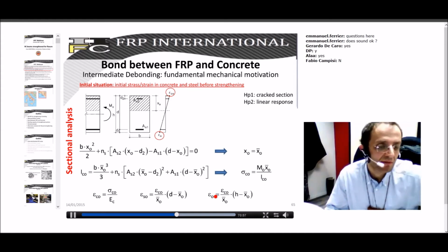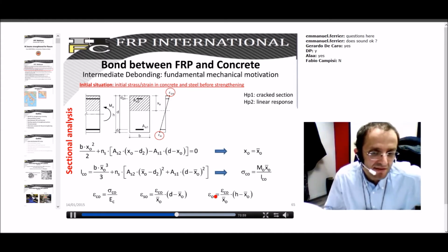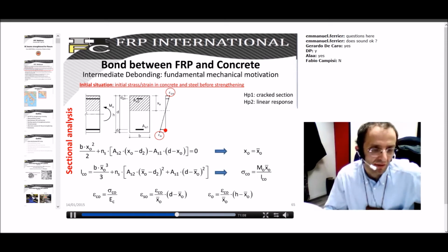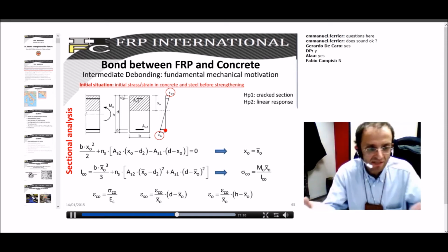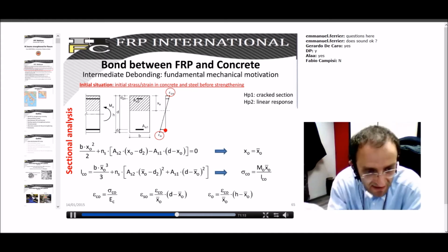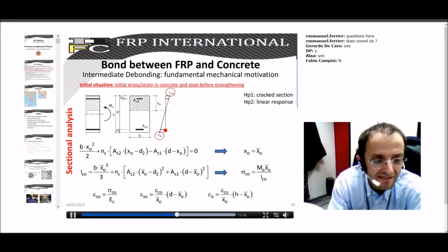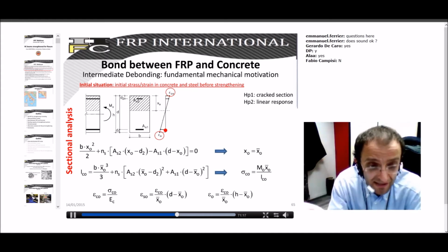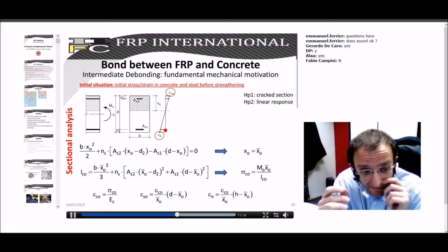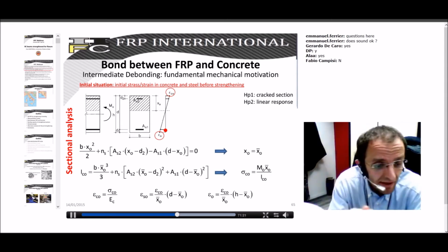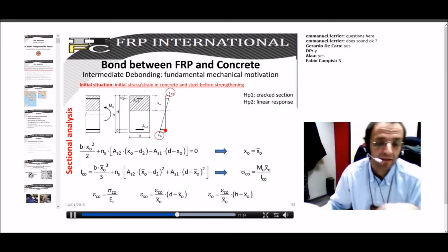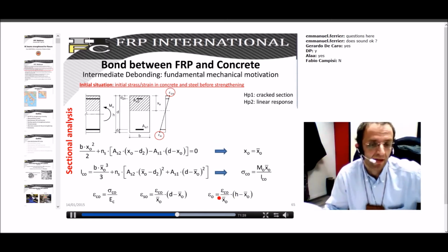Epsilon zero is an important parameter because this is the epsilon which is developed in the bottom chord of the section when you apply your FRP strip. So the FRP strip, when you apply it, has no axial strain inside, but the member to which it is applied is already characterized by this epsilon zero. So you have to take this into account.